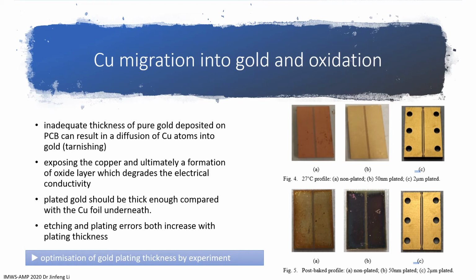Figure 4 here shows the gold-plated substrate at room temperature. After 200 degrees of baking for 20 minutes, the same groups of substrates are inspected again, with the profiles illustrated in figure 5. Compare figure 5b with figure 4b for the 50 nanometer gold-plated substrate. Tarnishing occurred after the 200 degrees heating as the copper atoms migrate into gold, which is an irreversible process, and raises a problem of copper oxide layer formation and dramatically increases the resistance.